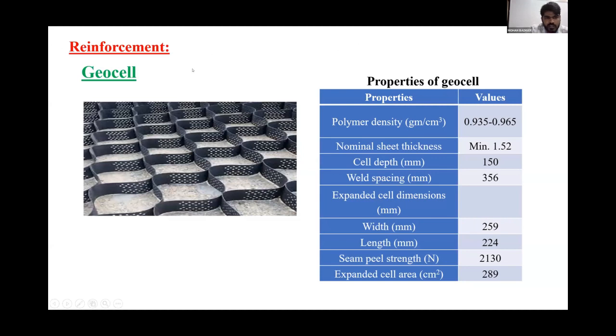The reinforcement material used is a geocell. Geocell of aspect ratio 0.67 was used in the study because, from the literature, it is observed that geocell with an aspect ratio of 0.67 to 1 will contribute to maximum benefits in terms of reduced plastic deformation and increased pavement performance. So in this study, we have used the aspect ratio 0.67. The various properties of the geocell are shown in the table. It has a cell depth of 150 mm, weld spacing of 356 mm.